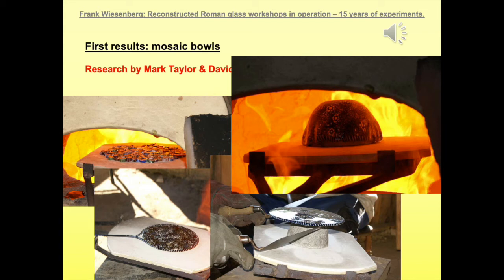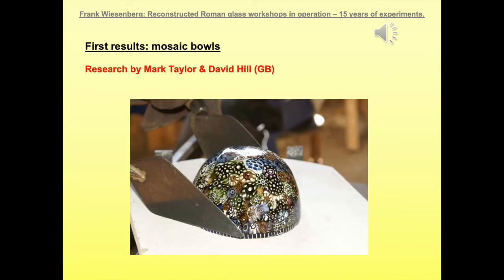This flat disc is then transferred onto a preheated hemispherical mold with some vegetal matter inside, and is then slumped over this hemispherical mold inside the glass furnace. For this task, some tools can be used, such as trowels or pincers. After frequent reheating and manipulation procedures by the glass maker, this vessel blank is transferred into the annealing oven, still on top of its hemispherical mold.